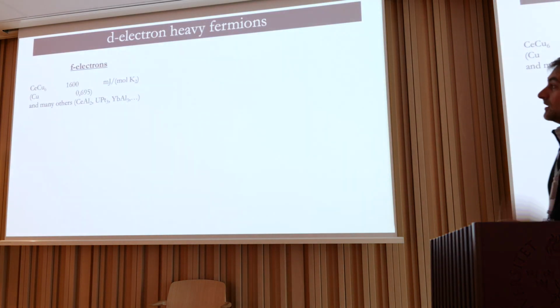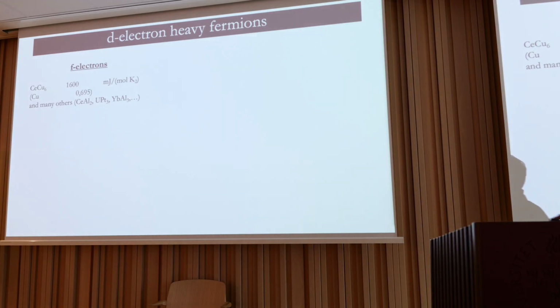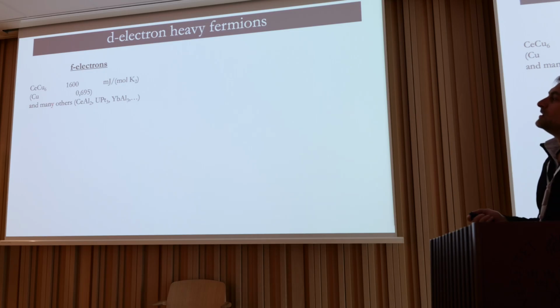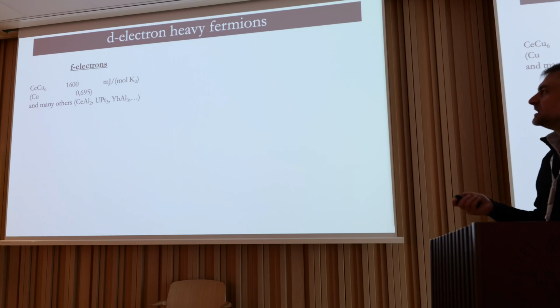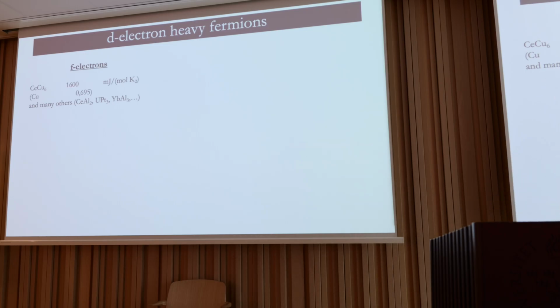Heavy fermions—I guess we all know there are many. Here's something I liked: cerium copper 6 is an F-electron compound, and just by inserting one atom of cerium into a matrix of copper, you go from a specific heat—this is the Sommerfeld coefficient, the slope of the specific heat going toward zero temperature—from a small number, 0.6 millijoule per mole Kelvin squared, to 1,600, which is one of the main hallmarks we look for in heavy electrons. This huge specific heat means huge density of states of the quasi-particles at the Fermi level, very heavy masses.